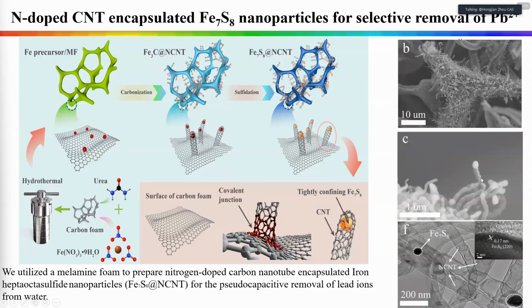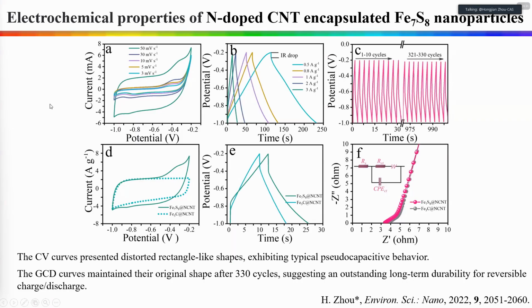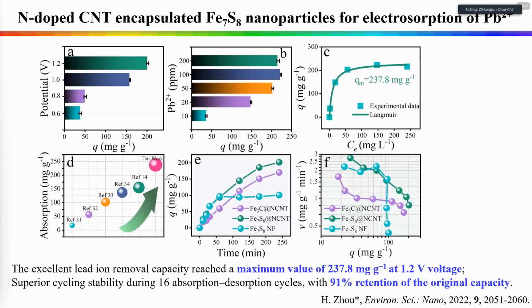In this TEM and SEM image, we can see that the carbon nanotube covered our material inside. All the Fe7S8 material is encapsulated inside the CNT material. So this is the electrochemical property of our material. We can find the CV curve presents a distorted rectangle-like shape, exhibiting typical pseudocapacitive behavior. And also the GCD curve maintained its original shape after 330 cycles, suggesting that our material has outstanding long-term durability for reversible charge-discharge. So it can be used in CDI adsorption.